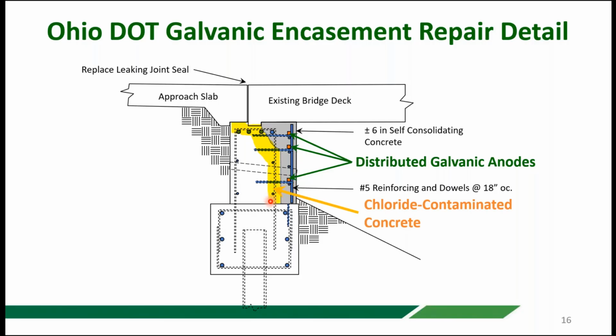And the reason they did that is because they were leaving all of this yellow chloride contaminated concrete in the structure. They weren't removing it. And the reason they weren't removing it is because this bridge was in service and they wanted to do these repairs without having to shore the structure or take the traffic off the structure or any of those kind of things.